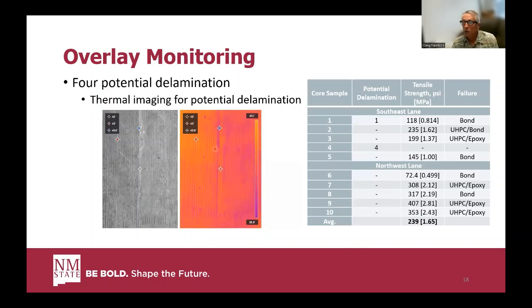So at the end of the project, we came back and looked at bond strengths, basically performed some thermal imaging to try to identify where some delaminations might be, if there were any. Also used chain drags. That's the lower tech thing, not nearly as attractive as the color photos from the thermal imaging, although the lower tech stuff is oftentimes more useful. There were 4 places where we felt that there might be delamination. And when we did pull-off tests, we looked at 2 of those locations, the first and the fourth. The fourth actually was delaminated, and that particular area was like a 2 foot by 2 foot section, so about 4 square feet that was delaminated.